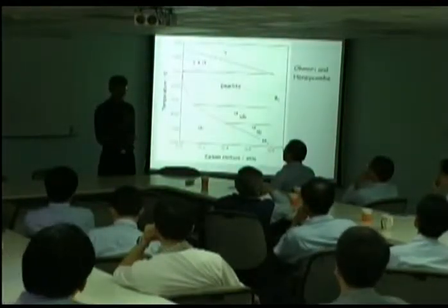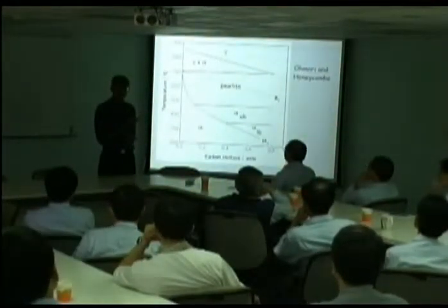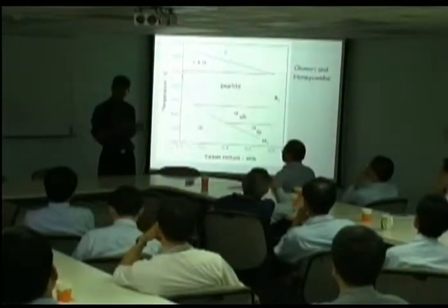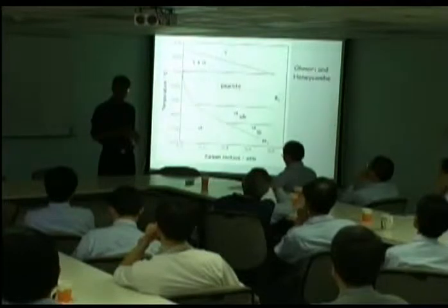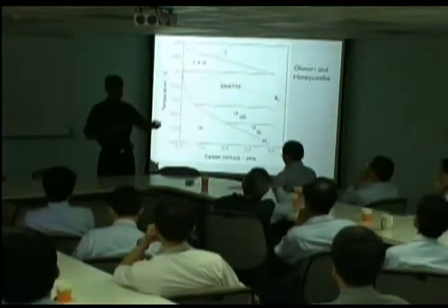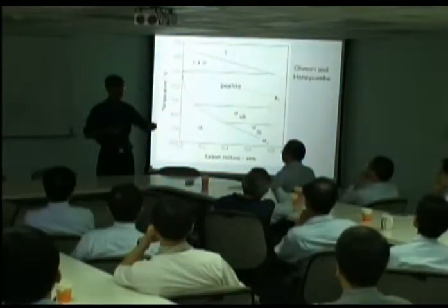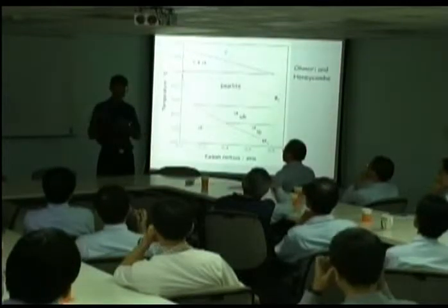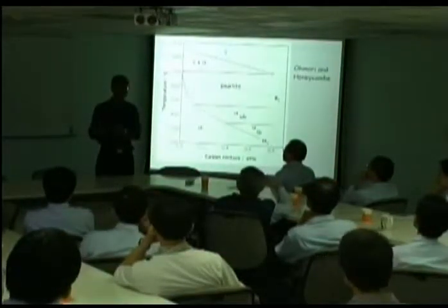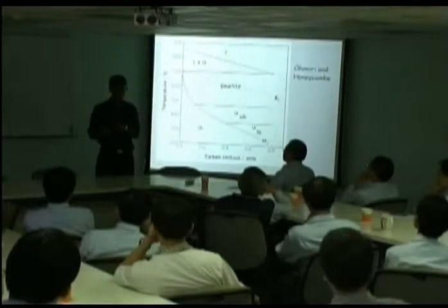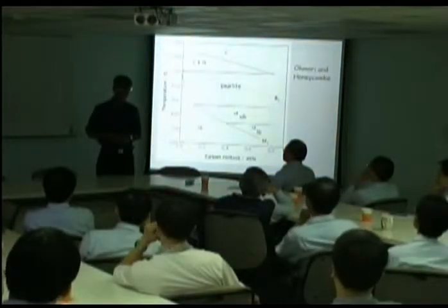People imagine that you always get pearlite, upper bainite, lower bainite, and martensite. But that isn't true. If you have a sufficiently low carbon concentration, you will not get lower bainite because the carbon can escape quickly before it can precipitate. If you have a sufficiently high carbon concentration, then the carbon can't escape fast enough and you will get a lower bainite microstructure.